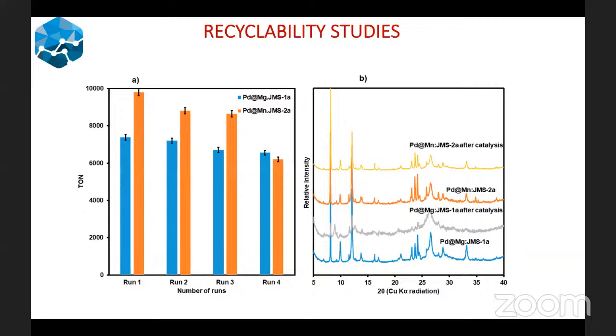And then we look at recyclability studies. Let's start with the manganese-based MOF, which I say Pd@Mn JMS-2a. When you recycle your catalyst, you can see that there is a significant drop in the turnover number. And that of the magnesium, it also drops gradually, but not as significant as the manganese-based MOF.